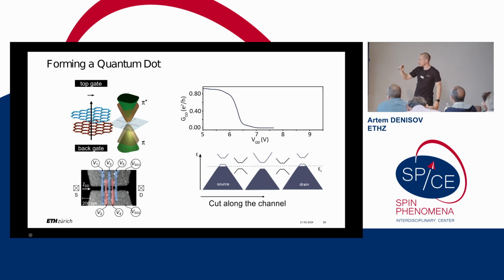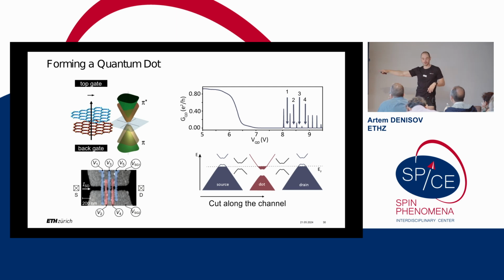But if you continue this process, at some point you will go to the N region very locally, meaning that nearby you're going to have two p-n junctions, which naturally create a quantum dot, a so-called PNP quantum dot. The formation of the quantum dot is very clear from these very sharp current or conductance peaks, which are called Coulomb peaks. Each new peak manifests the fact that a new electron can occupy the quantum dot. This is very standard quantum dot charge physics, which most of you know, which you can see in gallium arsenide and silicon germanium, but also in graphene. It just shows that graphene has pretty much the same quality from the charge perspective.